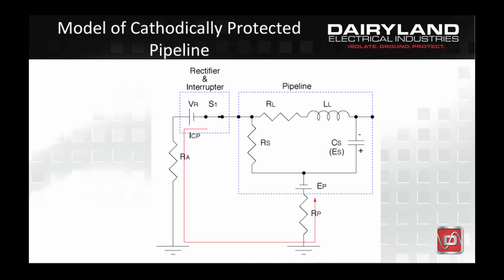When the rectifier is on and the switch S1 is closed, DC cathodic protection current flows from the anodes through the earth to the surface of the pipeline, causing the pipeline to polarize. The term polarize simply means that a potential is developed across the pipe-to-soil interface that tends to oppose the flow of current, as represented by the charging of C sub S to a voltage designated by E sub S in the schematic. I have taken some liberty with the normally used subscripts for some of the terms in an attempt to simplify them.